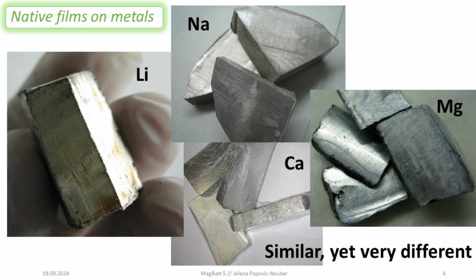So look at these kind of surfaces of the metals. They all look kind of the same. For the ones that worked with these kind of metals in the lab, they of course tactilely know that these have very different hardness, first of all. So for the people that had to shape their calcium electrodes in the glove box, I am saying hi to your hammer hands, right? It's much, much harder. Magnesium and calcium are much, much harder than lithium and sodium. So in the case of sodium, we can really nicely shape it, roll it as a kind of a cake and cut it out, etc. But in the case of magnesium and calcium, these are much, much harder. But their surfaces seem to appear quite similar if you get them highly pure and open them in a glove box, yet we do somehow expect that they behave differently.